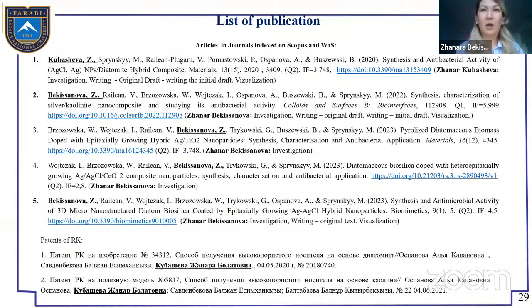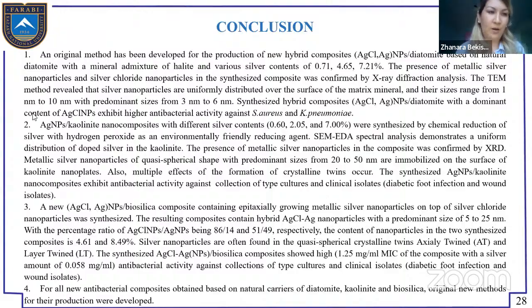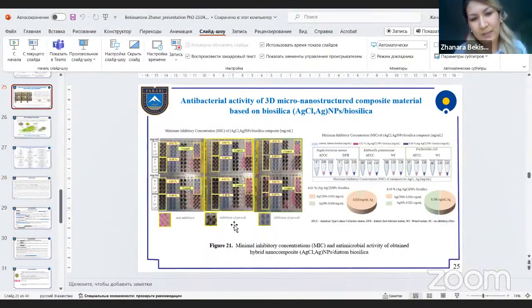In this work we dissolved the solution and used the dilution method with this concentration of composite, and we added resazurin. It is an indicator showing where bacteria died, or where there is growth inhibition or non-inhibition, in this method.